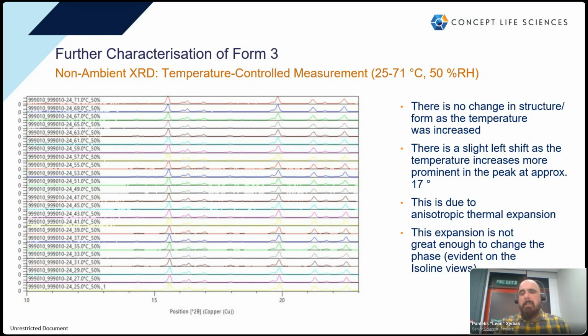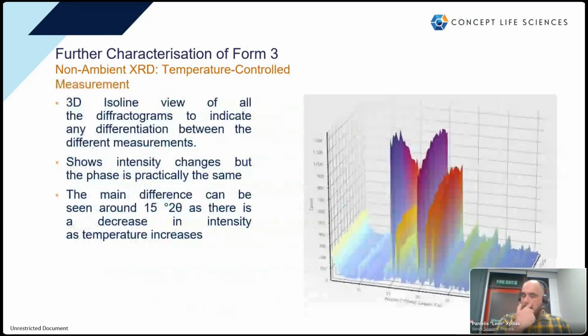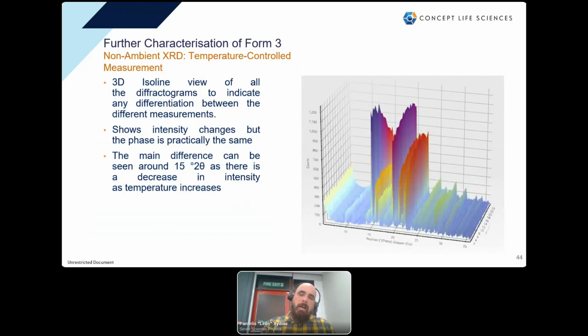phase, but you can also see it more significantly, this differentiation on the 3D isoline view, where we can see that there is a drop in the counts, which is normal. It happens when you are hitting a crystalline material, but it's not a great differentiation. We can say, though, that it remains stable at normal temperature conditions.